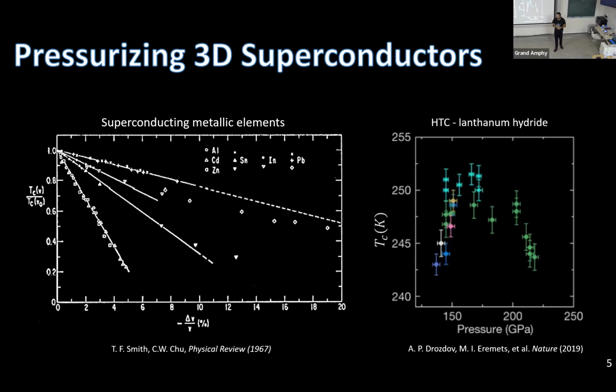There are many explanations of what exactly pressure does, but from what I found in many papers, the main common thing is that under pressure, we couple different regions in the system. Many high temperature superconductors are layered materials. You make the atoms closer and thus increase the coupling between the different regions. So many experiments were done on 3D superconductivity. The common way to do so is by diamond anvil cell.